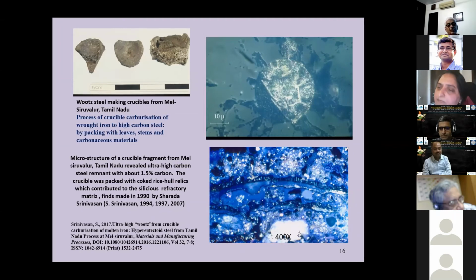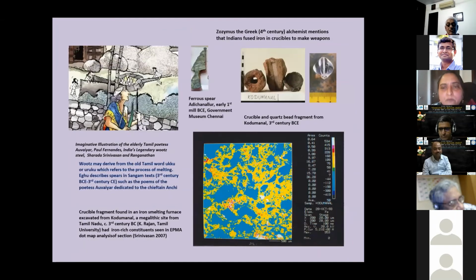And the other aspect is that when you look at the crucible matrix, of course, it is siliceous, but it also has these rice hull relics, because the process of carburization of the wrought iron was done by packing it with all these carbonaceous materials in a reducing condition. So in a way, there are these parallels which also come to mind when you look at the wootz process.